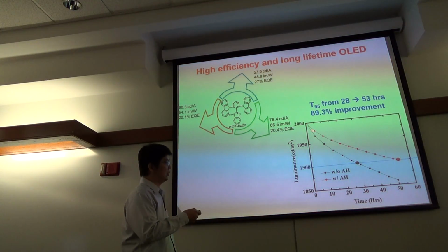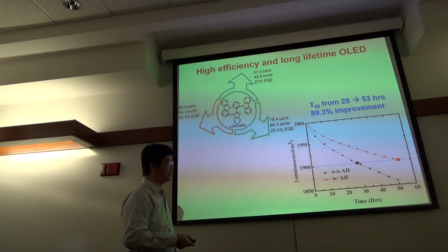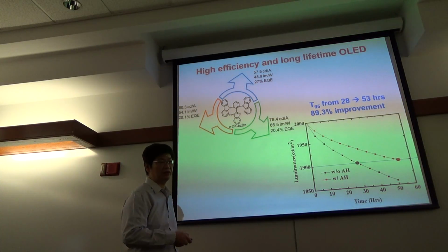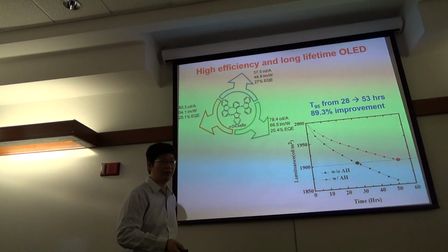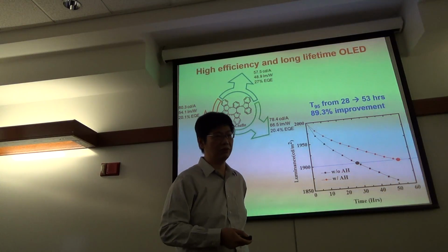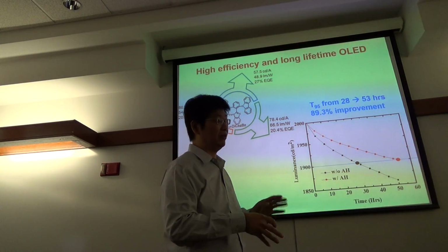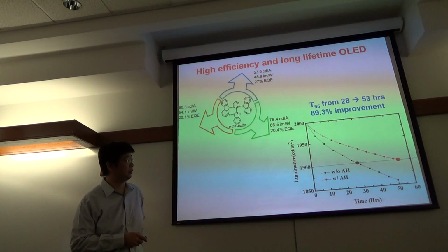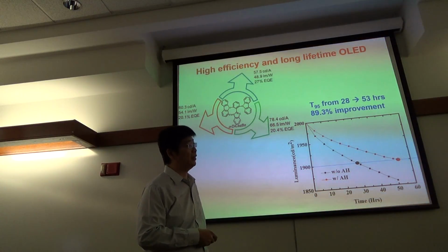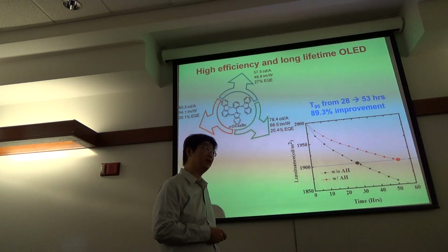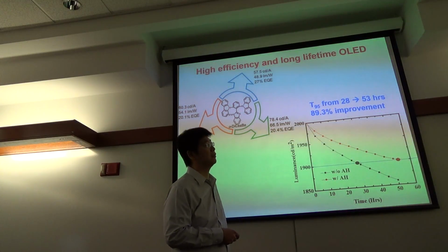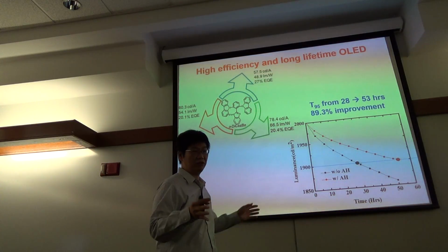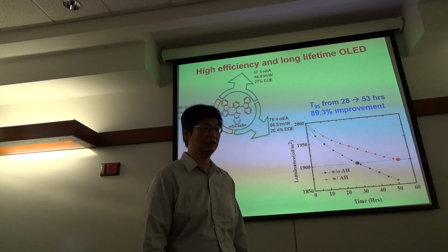Because it's also a collaboration with industry, this is right now used for the product. Which means we can improve the lifetime performance by almost 2 times with just some modification in their structure. What's the wavelength? The peak is at 470, and the full width at half maximum for the material itself is around 70, but you can use some cavity to reduce it to lower 50-something.